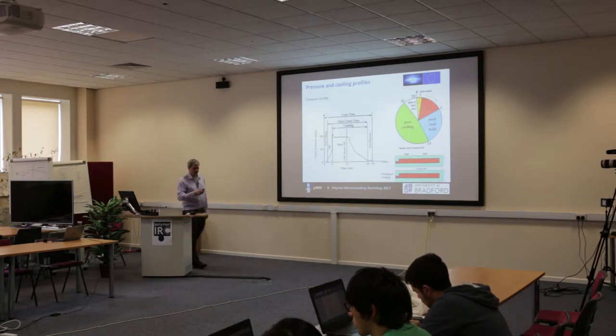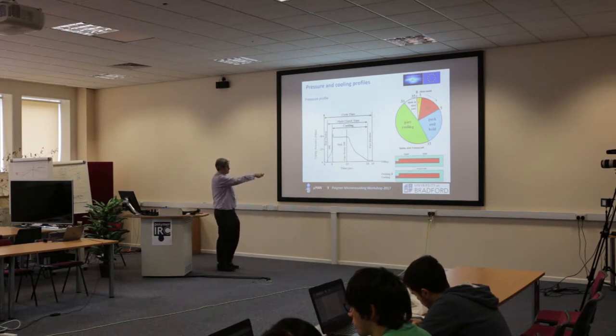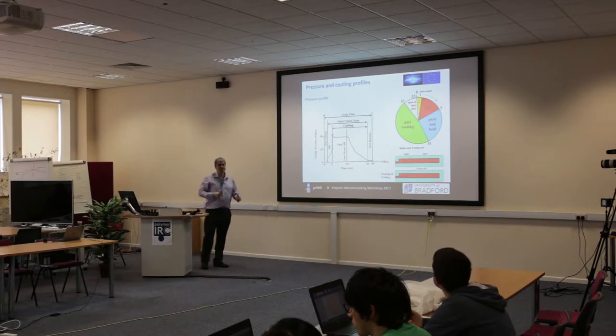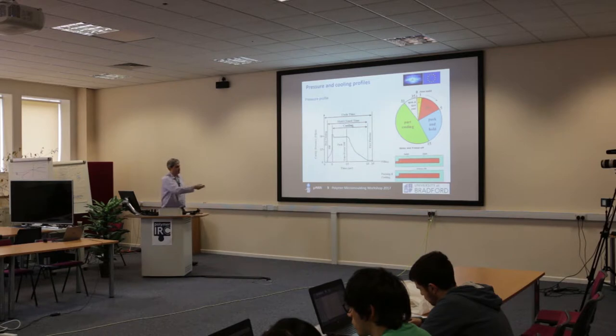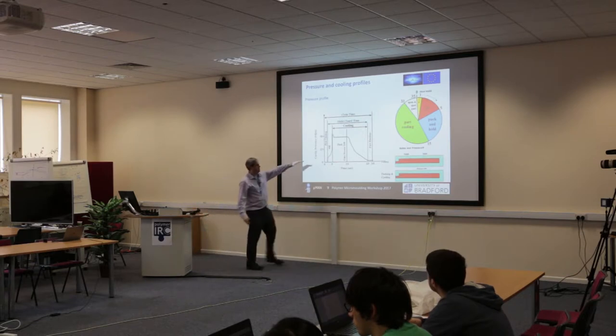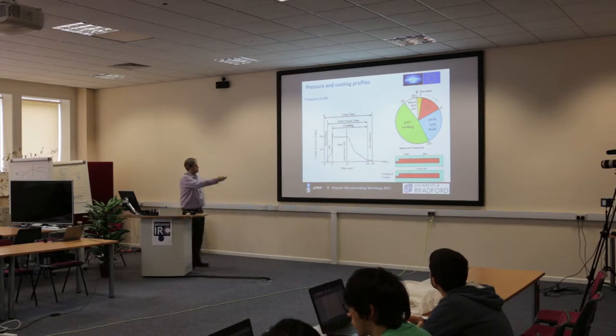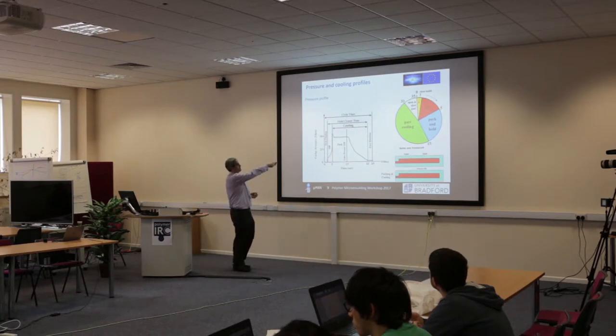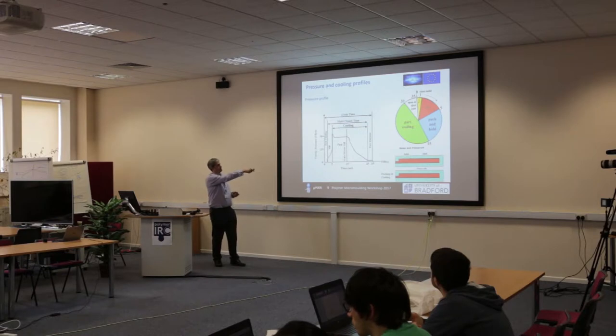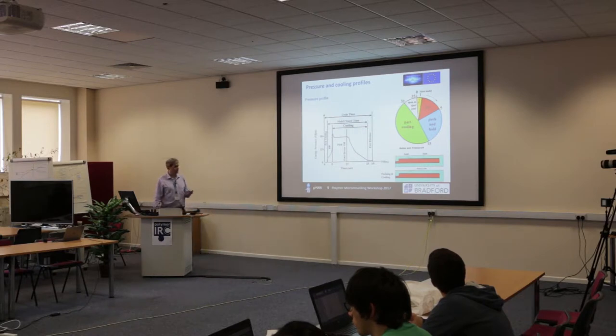A typical pressure profile through the cavity shows the initial fill region, where the gradient is an artifact of the cavity geometry — different increases in filling pressure correspond to different cavity sections. A thick section gives a shallow pressure gradient; a thin wall or narrow section requires a high pressure gradient. At approximately 99% fill we switch from velocity control to pressure control, sustain that hold pressure to account for shrinkage, and once the gate has frozen, we enter the cooling stage where pressure drops off to zero and we can eject the part.